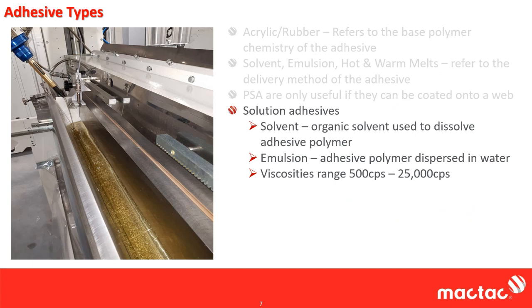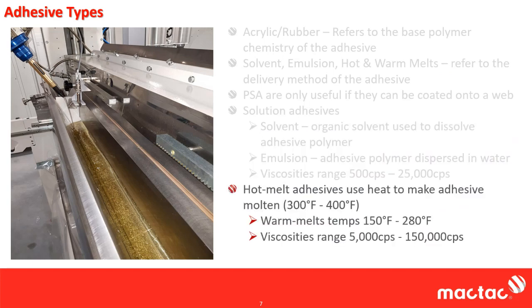One solution adhesives is one solution where we're actually dissolving the polymer into a solution to make it coatable. Another way we could do this is to turn it into molten form, which is your hot melt adhesives. With hot melt, we're melting them at about 300 to 400 degrees Fahrenheit. We're making the adhesive molten, so it's down to a coatable viscosity.